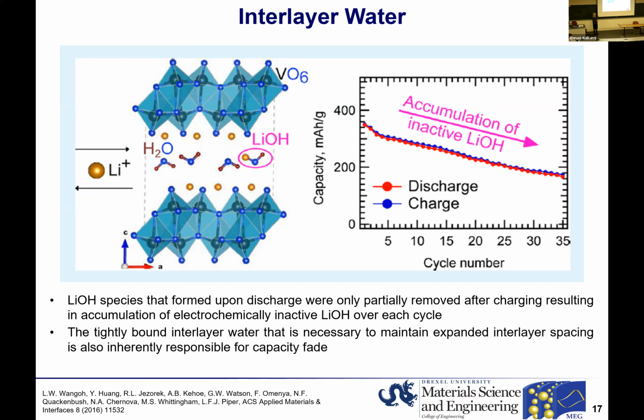And the group of Louis Piper, who I just learned moved from the United States to Europe, has shown that when using the parent bilayered vanadium oxide with water molecules only as an electrode in lithium-ion batteries, they observed the poorly reversible formation of lithium hydroxide in the interlayer region, which due to this poor reversibility led to significant capacity decay. So I'm using this example just to show you one of the mechanisms why water might be bad. And in the case of our materials, we already know that all ions get pre-intercalated together with a water shell. So is there a way to minimize this interlayer water content?